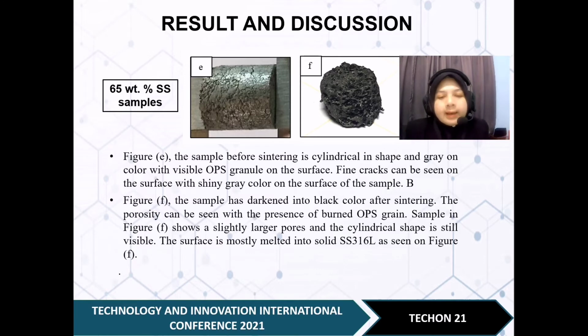Okay, then also, we can see the sample before the sintering is grayish, and after the sintering, the sample is darkened into black color. The location of the sample during the sintering is far from the argon gas, so this sample tends to be exposed to oxygen. The sample in figure F has slightly larger pores, and we can see the larger pores and the cylindrical shape is still visible.